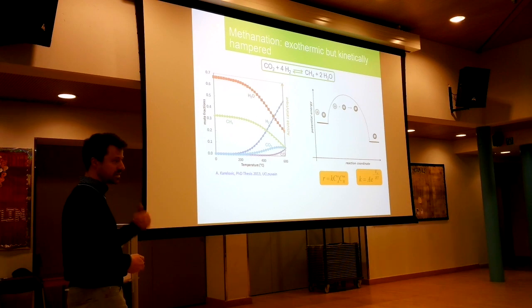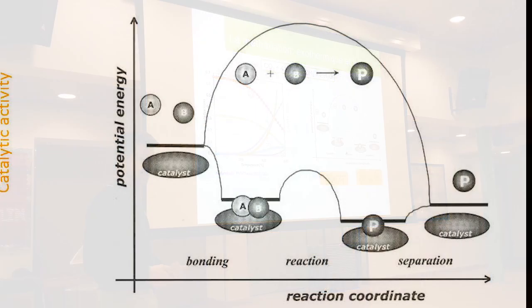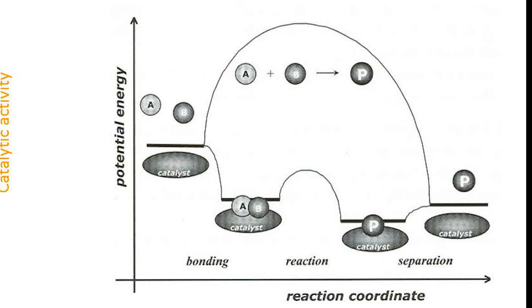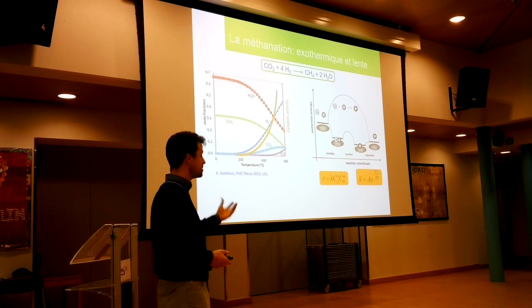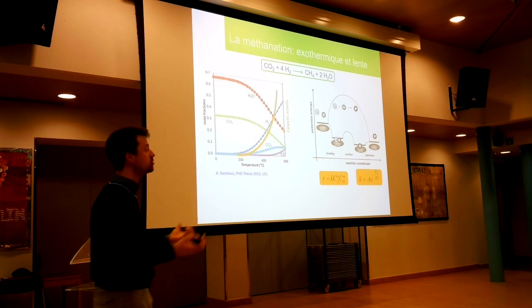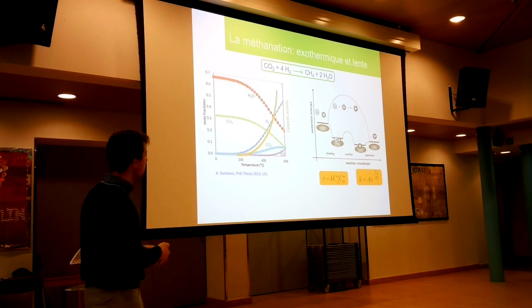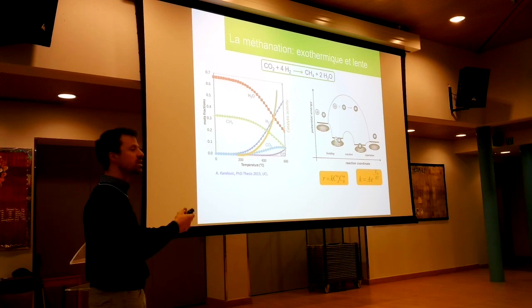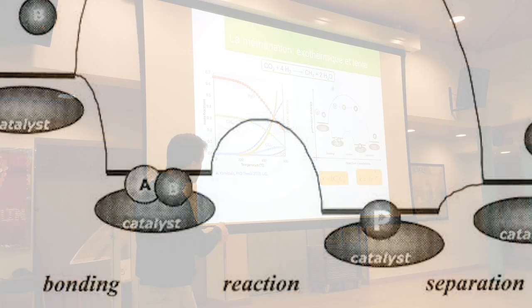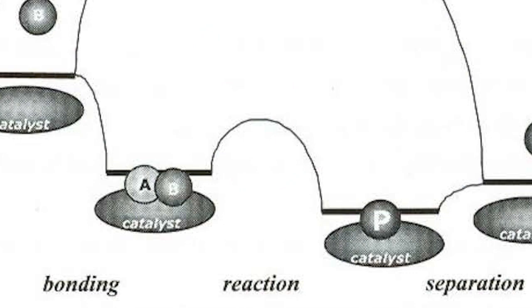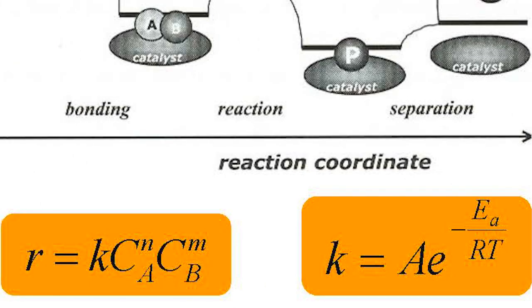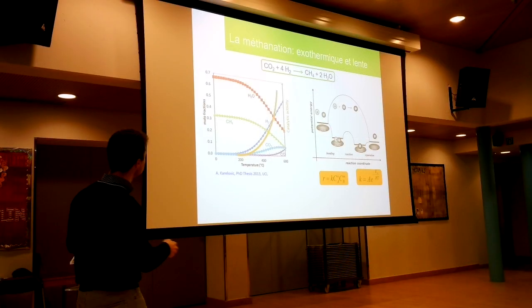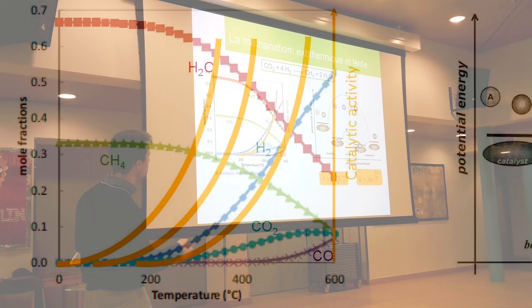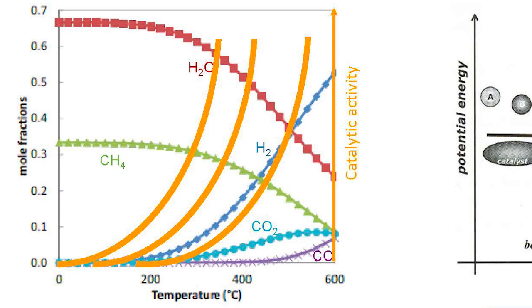So what we do as catalysis scientists is to try to find good catalysts that will have a good affinity for those two molecules. In this case, it's the ability to dissociate hydrogen, to dissociate or to activate CO2. And then they're put in a situation where it's easier for those two molecules to react with a much smaller energy of activation. Small energy of activation, large exponential, large K, large R. Okay? So if you don't have any catalyst, what you see is that the catalytic activity, so the rate of the reaction, is zero. If you have a catalyst, so that's the way here, you start to see some activity and it increases, of course.